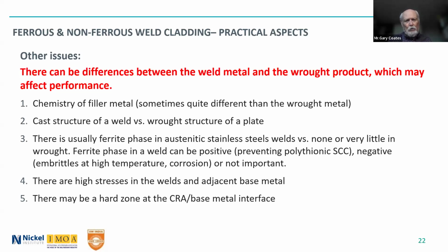Of course, with weld overlay, you have high stresses in the welds and the adjacent base material that may or may not be of concern. And there may be a hard zone at the CRA base metal interface. So if you use 309, you can get a very thin area where you have some martensite present, and that may affect the properties if you're doing any severe forming operation of the piece. It's just something to be aware of. You can't assume that, okay, I can just treat it like solid material.